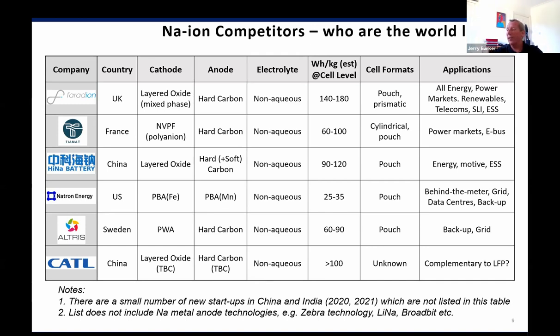Company called Natron Energy in the States is a spin out of Stanford University. Again, we know these guys quite well. They're taking a completely different tack on this. They're not attacking the high energy applications. They're going for power and lifetime applications with low cost. So they're using Prussian blue analog on both sides of the cell, an iron-based Prussian blue on the cathode and a manganese-based system on the negative. The specific energies there are 25 to 35 watt-hours per kilogram. That's the same range as lead acid. But they're looking at very high lifetimes and looking around these data center applications, and they've got probably more funding than any other company working in the sodium-ion space right now.